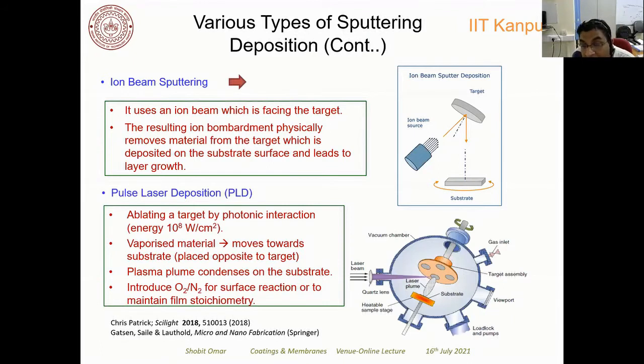Then there is also another variant which is quite extensively used to make thin films of dielectric materials, the PLD technique, where you ablate the target material with highly energetic photons. You can see that they can have a high energy of 10 to the power of 8 watt per centimeter square. Once this laser beam strikes the surface of the target, a plume of plasma is formed, and this material absorbs the energy, and this plume gets condensed on the substrate, which is present at a certain angle. Also, this substrate is heated, and that will control the nucleation rate of the thin film that is deposited on the substrate.